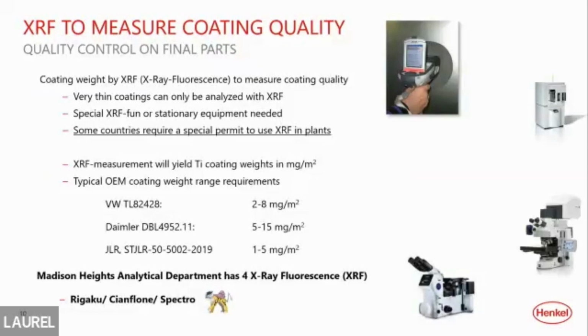This is how you control it, because it is aluminum and these coating weights are 1 to 15 milligrams per meter squared. You can't see this coating. I mean, it's just a little bit of something. And so we have to measure it with an XRF gun. The XRF gun has to be calibrated with titanium standards that we recommend. You get the titanium standards from Micromatter in British Columbia, and you calibrate it every day, or else your supplier or your customer won't be very happy with you, because our customers, the OEM suppliers that we do this for, are pretty specific that you document that you are getting this dialed-in coating weight.